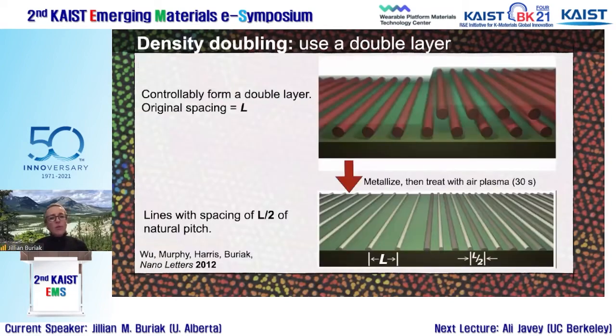But what we are wondering is if we could hack this. And so the way we hacked this was by creating, in this case for cylindrical arrays, we would double that single layer to form a density doubled layer. And so when we then take these cylinders of, let's say, polystyrene-poly-2-vinyl pyridine, we metallize them and treat them with air plasma.